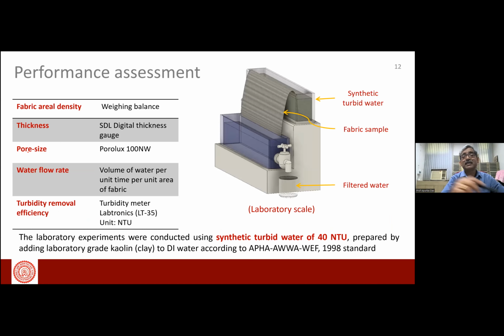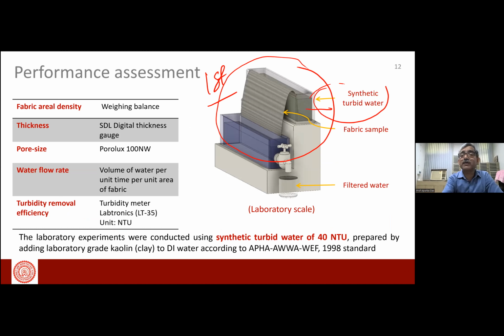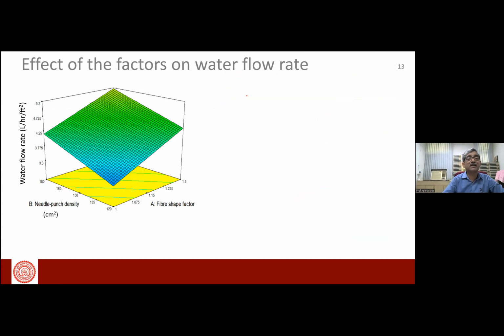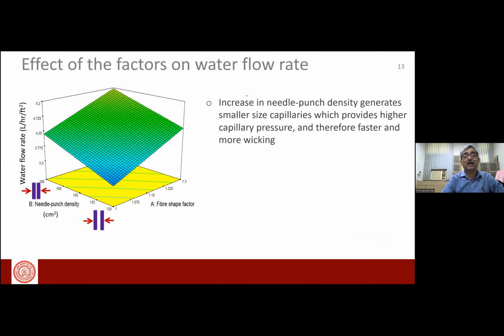And finally, this is the system, the first stage filtration, where this is the turbid water. This is the synthetic turbid water we have used, made with synthetic clay, and you can see it's a non-woven fabric sample. Against gravity, when the water is wicked, we get the first stage filtered water here. Simply by flowing the water along its length, we could achieve more than 90% turbidity clearance.